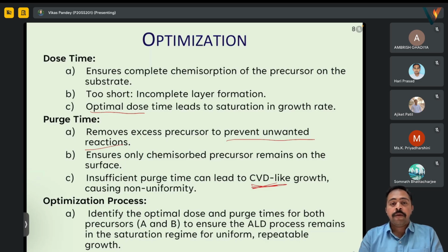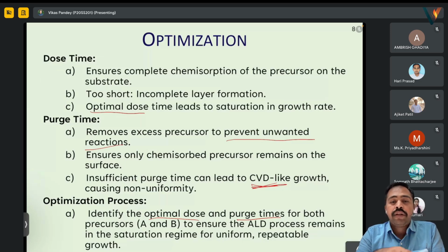It should not be like we are purging so much that even the chemisorbed precursor actually moves out, pulling out everything. That should also not happen, and many times the precursors are gases. So the optimization process is to identify the optimal dose and purge time, and it may not be the same for precursor A as well as precursor B, so that the saturation regime of ALD is reached. That means the reaction is happening at its optimal rate, so that we have uniform and repeated growth.